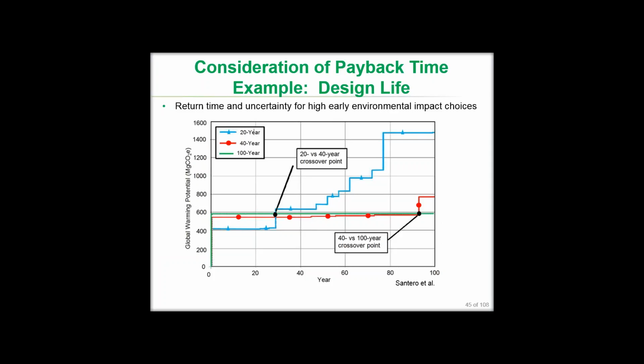So the real difference why the 20-year design life needs that asphalt overlay at about 28 years and the 40-year design life doesn't need it till much later is the rate of cracking predicted by MEPDG, which is primarily a function of the slab thickness here. So that extra hit in global warming potential is that extra 4 inches of concrete primarily, and the tiny part associated with construction, but it's mostly the cement for that extra 4 inches. But what that extra 4 inches gets you in this case is a much slower rate of fatigue cracking.